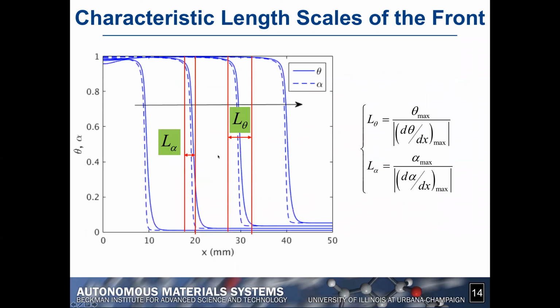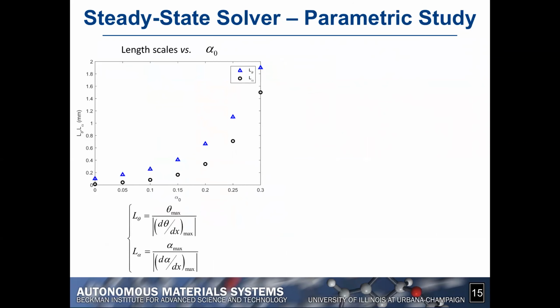We can use different ways to define these, and the ones we decided to adopt are the ones on the right-hand side, which are typically the kind of length scale that is introduced to define the length scale associated with a shock in fluid mechanics, for example. And so what we can do is obtain the variation of these two length scales with respect to the initial degree of cure alpha 0, as you can see on this figure. And you can see that as you pre-cure the polymer, meaning as you have a gel that is more and more pre-cured, the length scale of the front becomes less and less sharp. So the length scale increases as a function of alpha 0.